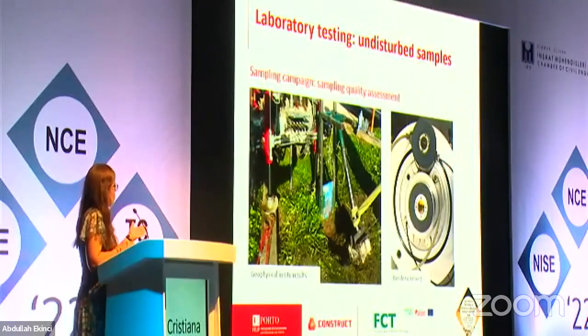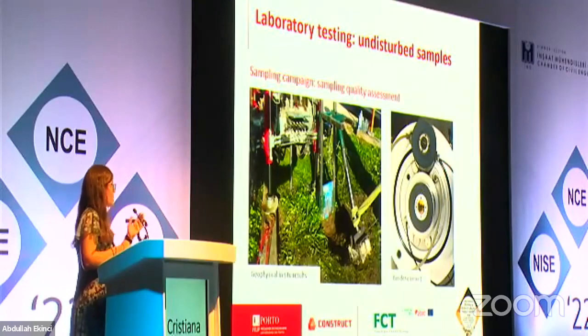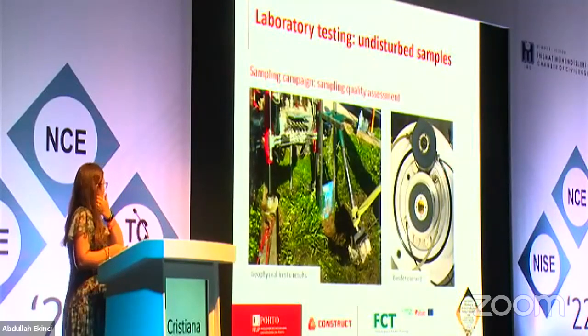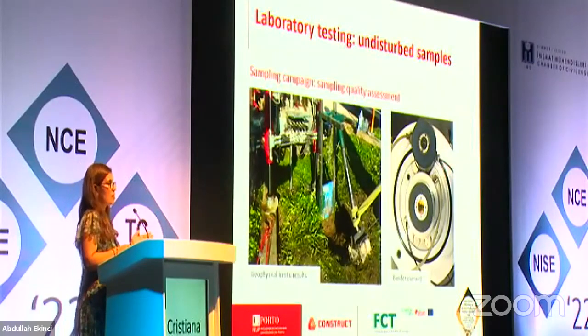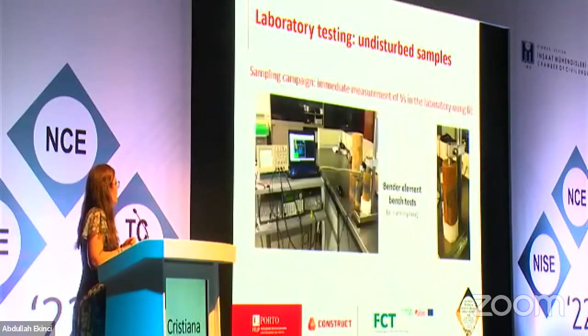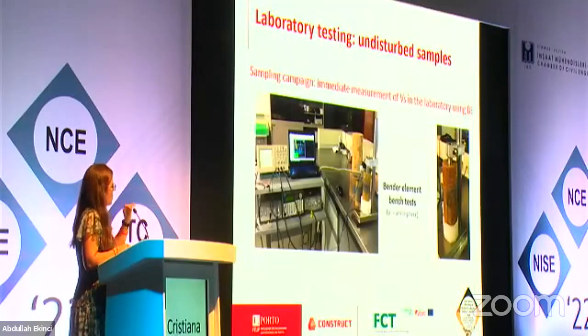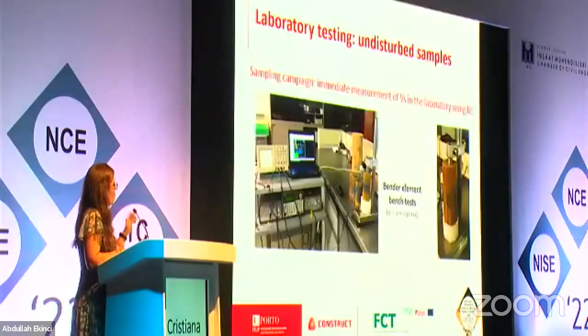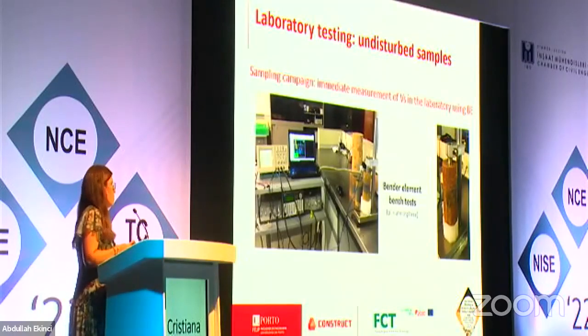So we use the data from the geophysical in situ tests. In some cases, we have SCPTU. In other cases, we have SDMT. We have cross-hole. We have a variety of geophysical tests, and we compare them with Bender element tests in the laboratory. So after each sample was collected, you see here, exactly with the PVC tubes, we made the measurements on the bench, so at atmospheric pressure, in order to have an idea of how the stiffness of the soil was immediately after extrusion.